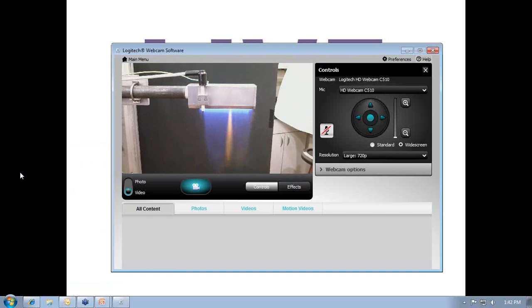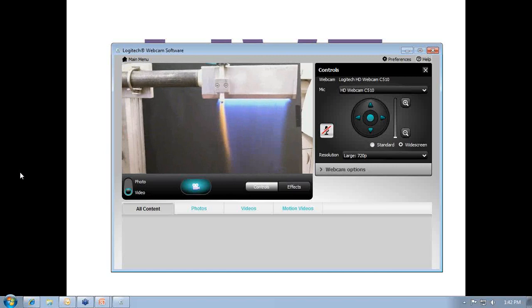Now that burner assembly, as you can see, will profile inner cones and an outer cone. The inner cones that you see, those greenish blue cones on the inside of the flame, are the primary treatment zone cones. You want to interface the surface of a material with the tips of those inner cones in order to affect the highest level of oxidation as well as the highest level of surface energy. The secondary treatment zone is there to allow us to treat, ionically and electronically treat the surface, but not to the highest degree. But the profile of that discharge also allows us to encompass a large profile, a large contour of material. Okay? All right. So that demonstrates our technology relative to air plasmas, flame plasmas, and variable chemistry plasmas.